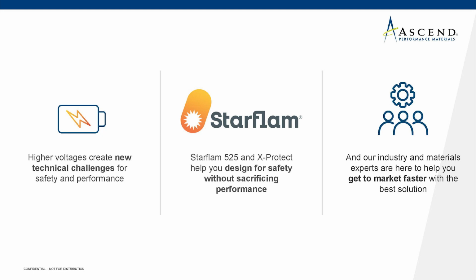So thinking about the lifetime of an electric vehicle, it's not just the drive cycle that we need to assess. In the past, automotive companies have been looking at heat aging data for, say, 3,000, maybe 5,000 hours. For electric vehicles, we also need to add the charging cycle to that heat exposure. So let's say roughly double the drive cycle time. We believe that with RTI 20,000 hours, we're really safe on that side.